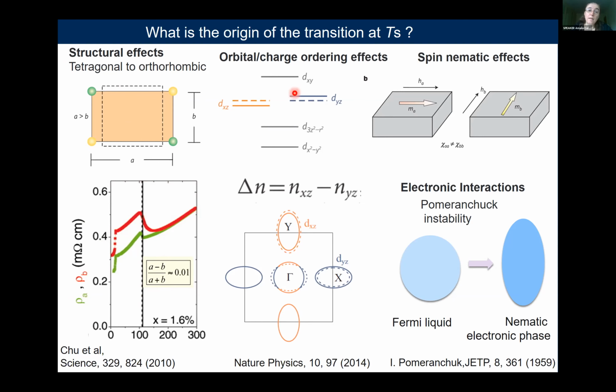The second candidate relates to the orbital degrees of freedom. The fact that in the tetragonal phase we have two degenerate orbital states, dxz and dyz, and as one goes through the transition, this degeneracy is lifted, and then we can develop a certain polarization due to the orbital degrees of freedom, which determine the occupation of different bands. So here we have the hole bands at the gamma point and the electron bands at the X point in this representation. And as you go through these transitions, you expect that these pockets will distort and their orbital occupancy will change.